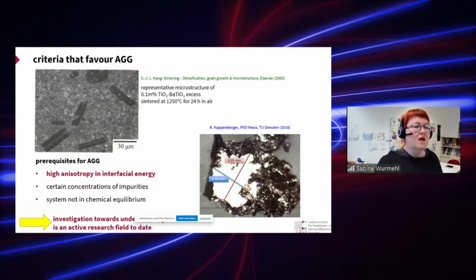This has been investigated in titanium oxide, barium titanate materials, as you can see here, where crystals grow on top of pressed pellets of the polycrystalline material. This is not well understood, but there are some empirically found criteria that favor abnormal grain growth. One of them is that certain impurity concentrations trigger abnormal grain growth.